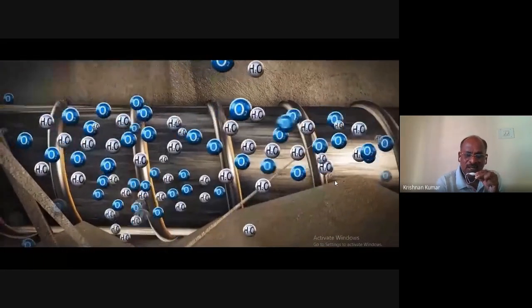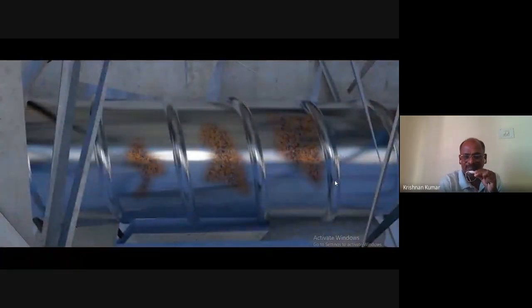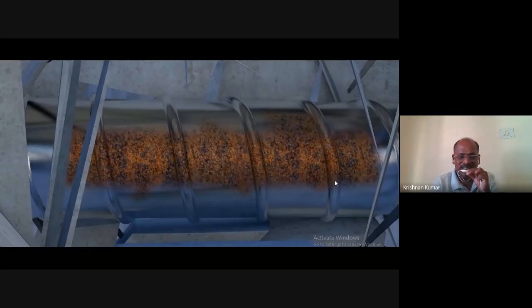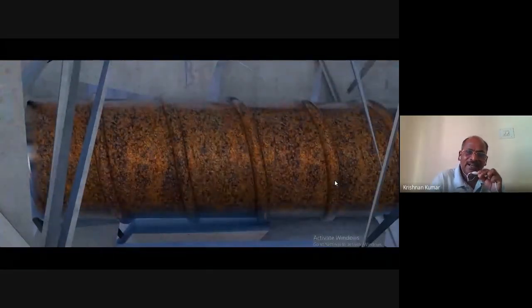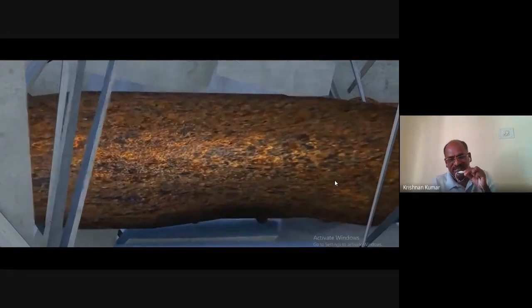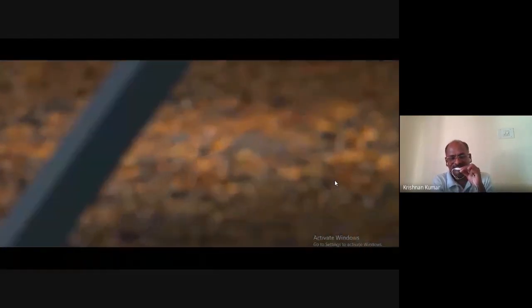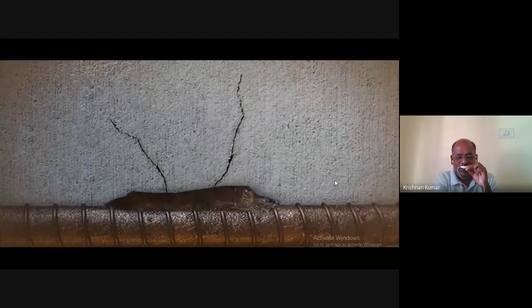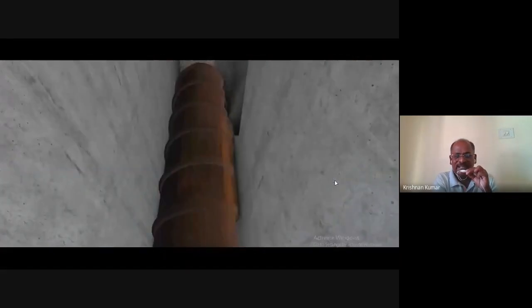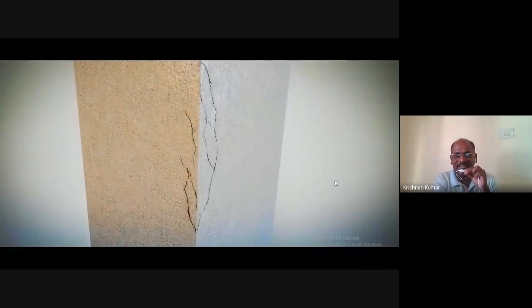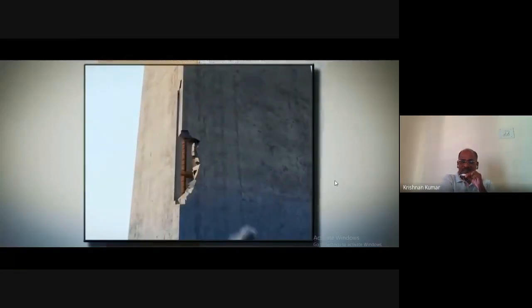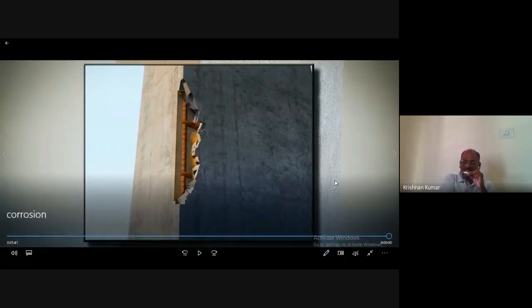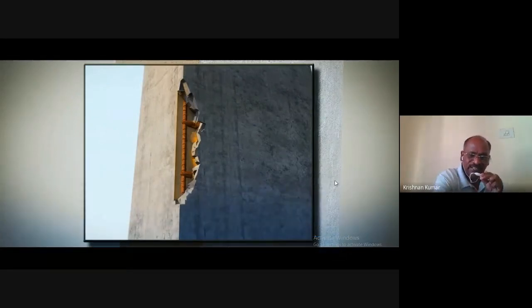Then initially with water and all these things, it will start corroding. A good, passivated reinforcement started corroding and it is propagating and reducing the cross section. You can see that the cross section reduction is happening. The corrosion product is higher in volume than the metal loss, so it exerts a pressure, then the concrete cracks. You are seeing the cracking. That is the way cracking occurs. Where the least cover is available, there the cracking happens. Then the steel reinforcement is exposed, which further corrodes, and finally the structure is going to fail. These are the general phenomena.